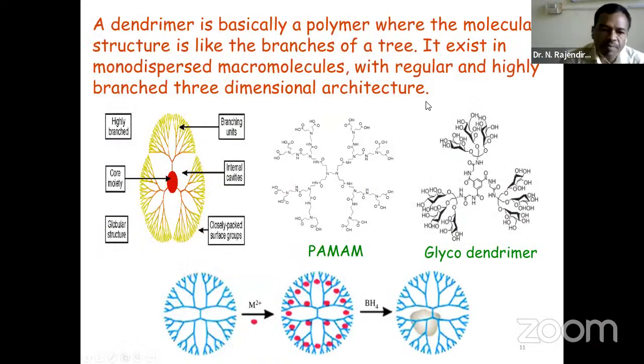And this is an example of another approach with a different stabilizing agent, that is the dendrimer, polyamidoamine dendrimer and glycodendrimers, where the dendrimer is a macromolecule that is entirely different from polymers. In polymers, we have a range of molecular weights in a solution, whereas in dendrimers, all the molecules are of uniform size. There are three regions: core, void, and branching units. Because of this scaffold, it acts as a very good template for the stabilization of metal nanoparticles.